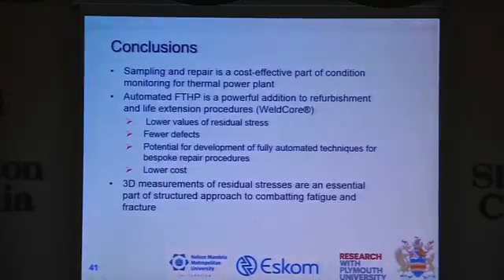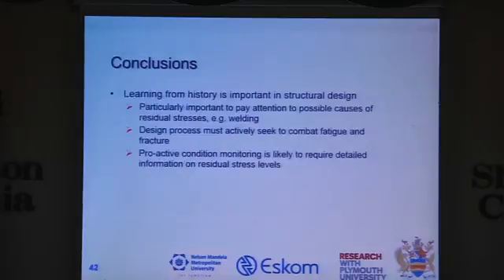In conclusion, then, sampling and repair is a cost-effective part of condition monitoring for thermal power plant. Automated friction taper hydropillar process is a powerful addition to refurbishment and life extension procedures. Lower values of residual stresses, fewer defects, potential for development of fully automated technique for bespoke repair procedures, lower cost. 3D measurements of residual stresses are an essential part of a structural approach to combating fatigue and fracture. And it is really easy to get large samples into places like the ILL.